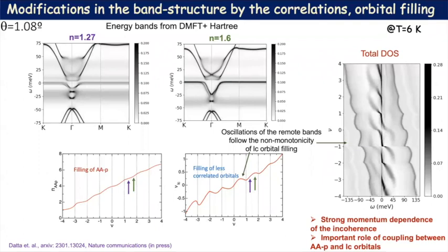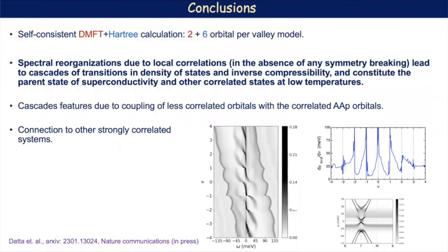And that brings me to the end of my talk. In conclusion, we have studied twisted bilayer graphene within a DMFT and Hartree calculation. The main message is that the spectral reorganization due to local correlations leads to this cascade of transitions that we see in the STM experiments and the compressibility, and that happens in the absence of symmetry breaking. Along with the correlations in the correlated orbitals, the coupling of the different types of electrons, the itinerant and correlated electrons, is also important.